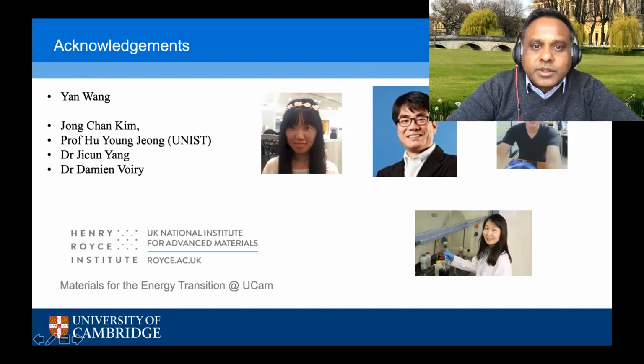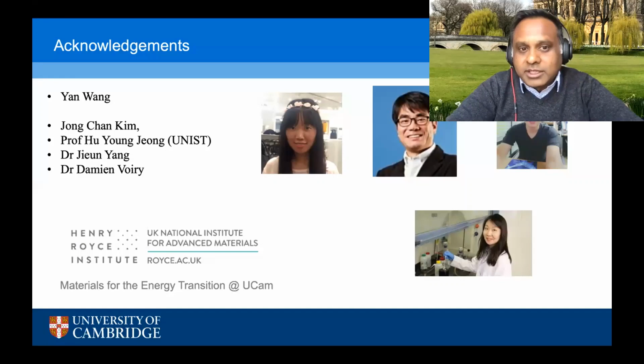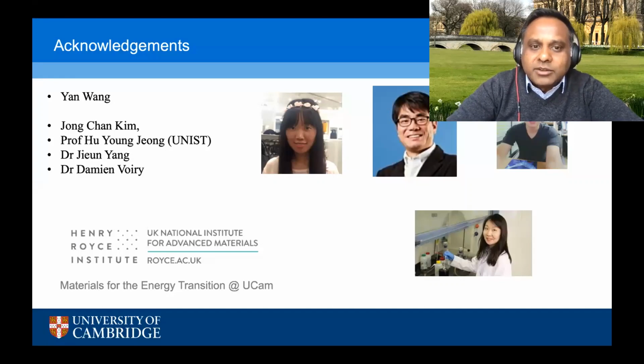If the indium is annealed in some selenium environment, could it form indium selenide or any alloy-formed 2D material? In principle, that's how these TMDs are made, but we've not seen any evidence of indium selenide. We looked very closely using XPS and other techniques, but at least within the annealing conditions that we use, we've not seen any alloying of indium with selenium.